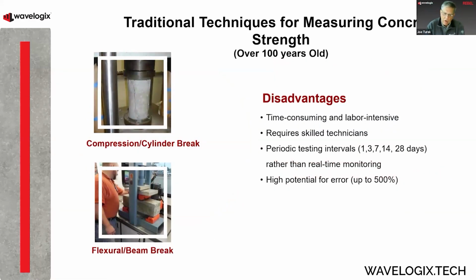When we pour concrete, concrete is great, but what we need to do to do our next operations is understand what the strength of that concrete is. When it cures, it's going to cure somewhere around 3,000 to 5,000 PSI, and really high strength concrete might be 10,000 PSI. But there's a lot of operations that we do early on, within the first couple of days.